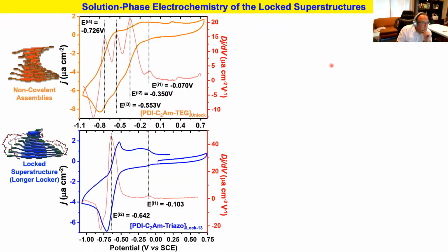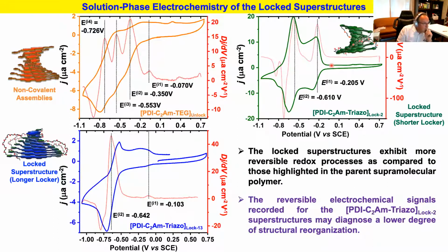Now, what's interesting is that we are also witnessing differences when we start looking at potentiometric properties in solution. What I'm showing you here are cyclic voltammograms that we have recorded in water, in an aqueous medium. When you compare the CV of the non-covalent assembly here and the CV of the locked superstructure, there is one important difference: once you lock the superstructure together, you start having electrochemical signals that are reversible.